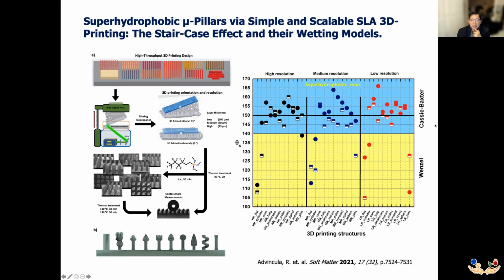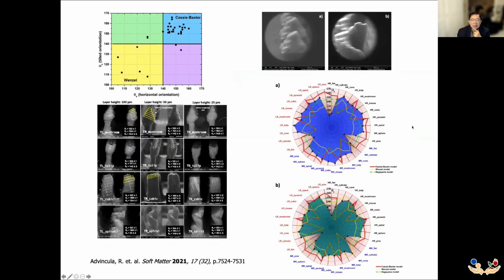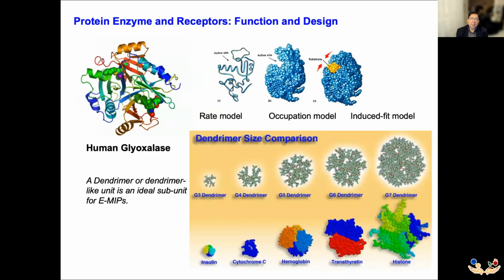high contact angles here. What this allowed us to understand is that the nature of the printing, the tilt, the volume, the features or staircase effect, and the surface chemistry all contribute towards the fact that super hydrophobic films can be observed from 3D printed films or matrices, and that means we can control the wetting behavior.